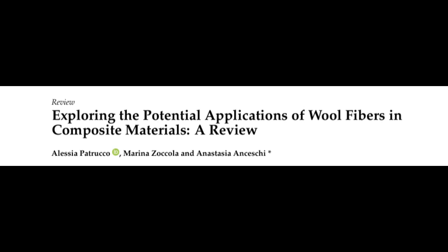What about the newer bio-based polymers? Are they pairing wool with those? Yes, absolutely. Exciting work there, too. In bio-based polyesters, using a compatibilizer like PVA allowed researchers to get over 40% wool content, which significantly boosted adhesion and stiffness, though strength at break was reduced, maybe due to short fiber length.